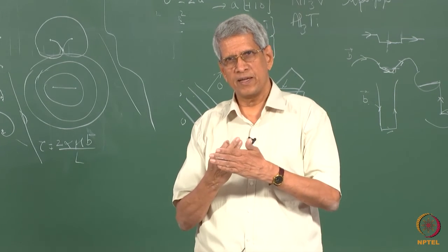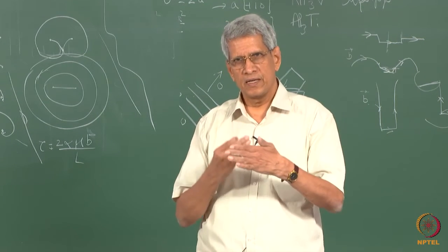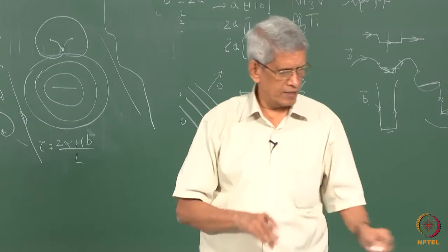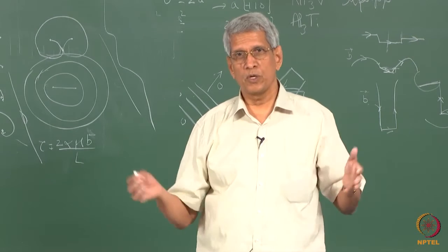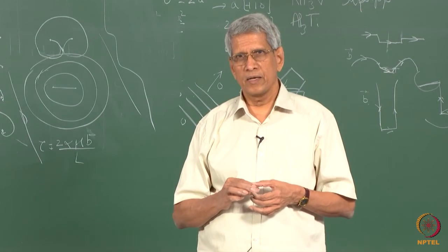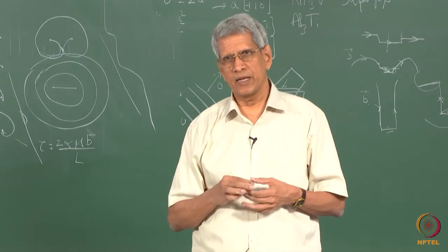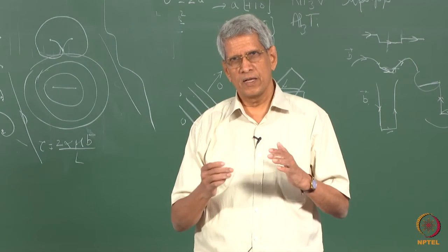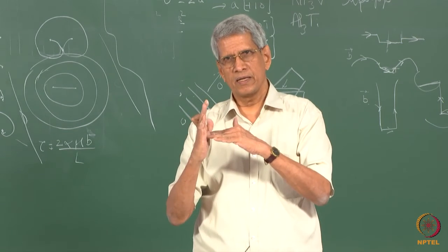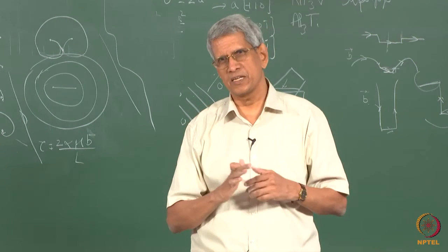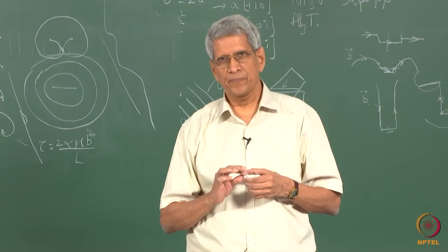When the stress reaches a value equal to the theoretical strength, the stress concentration from the dislocations will generate a crack in that. That has also been observed. Looking at samples in electron microscopy, one can see a planar arrangement of dislocations meeting at a particle, and one can see that a small crack has been generated in the particle.